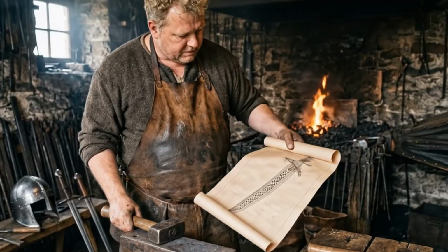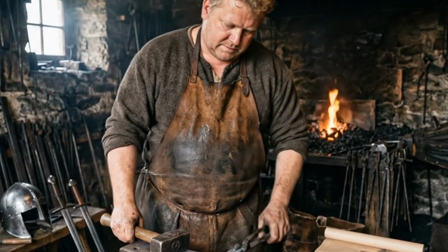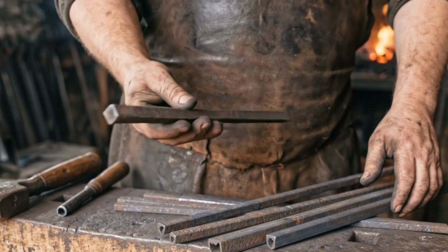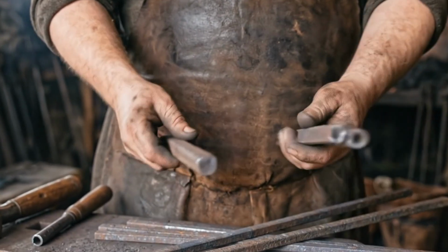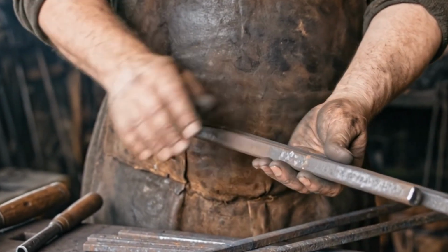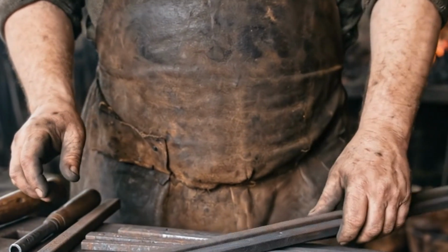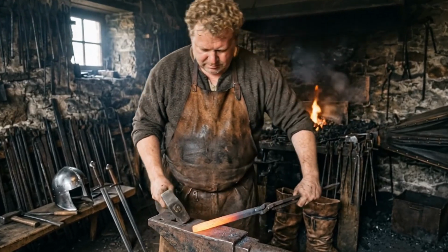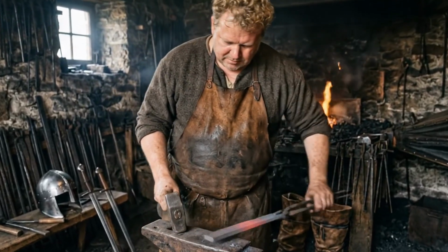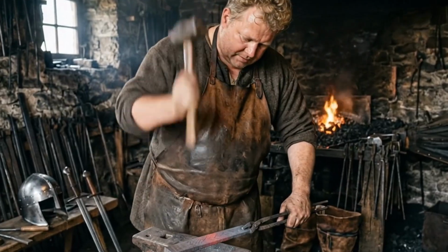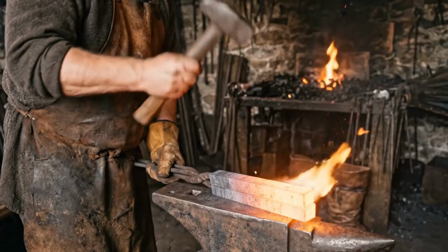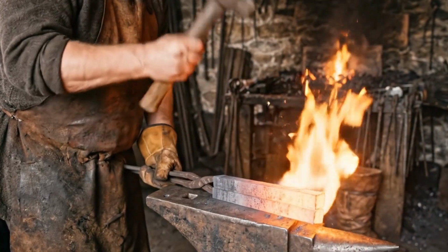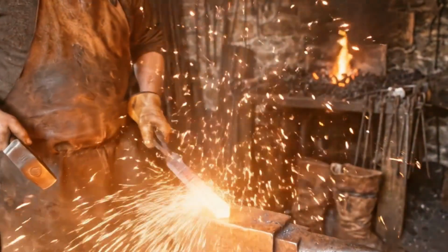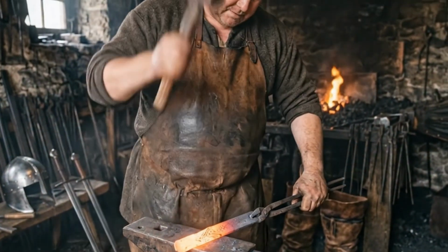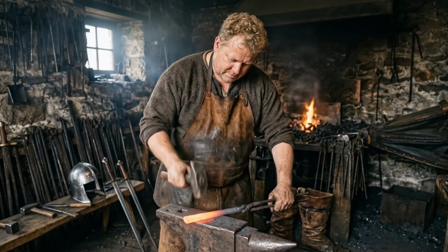They worked with the materials and knowledge available to them, leading to the development of pattern welding. This technique involved taking two or more types of steel with distinct properties. Typically, one steel with a high carbon content for hardness and another, often containing nickel, for flexibility and a brighter appearance. The blacksmith would stack these bars, heat them to a welding temperature, and then hammer them together until they fused into a single solid block. This process is known as forge welding.